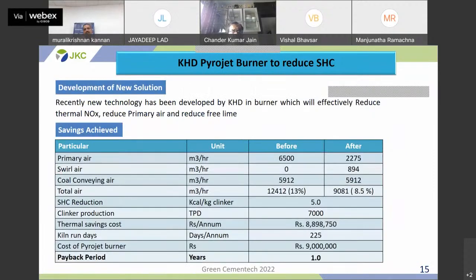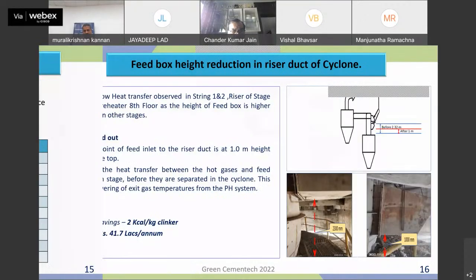We are using the latest technology KHD pyrojet burner, which effectively reduces thermal NOx, primary air, and free lime. By installing this burner, our total air consumption got reduced from 13% to 8.5%, and we have got thermal savings of 5 kilocalories per kg clinker. For this project, our investment was 90 lakhs with a payback of 1 year.